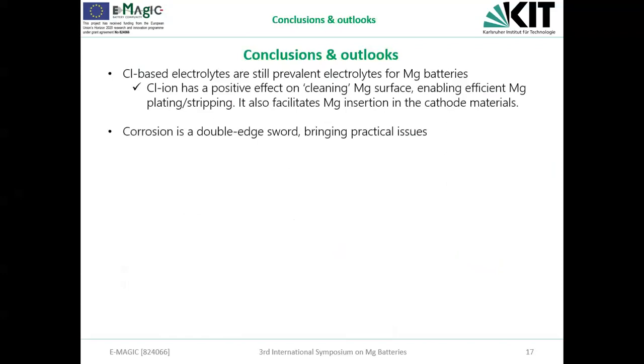To sum up, I would say that the chlorine-based electrolytes are still the prevalent electrolytes for magnesium batteries. The fact is that chlorine has multiple functions in the magnesium system, enabling magnesium plating and also insertion and de-insertion. Now it's still difficult to find, or there is no report about, additives that can replace the chlorine ions. But we should also realize that the corrosion issue is really the big problem, especially if we want to scale up the system. In manufacturing, for example, this will bring a lot of problems and needs more effort.